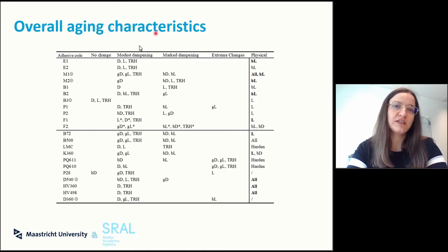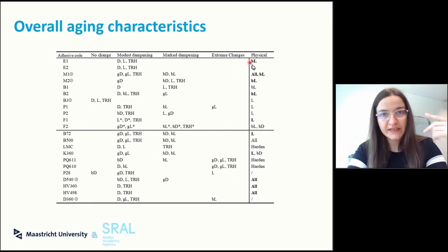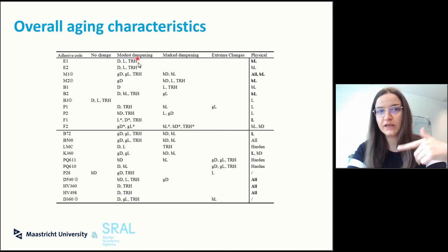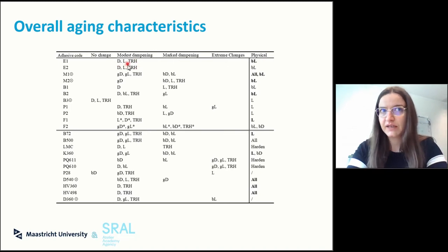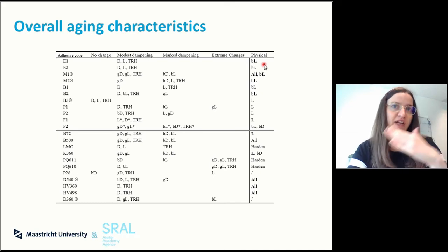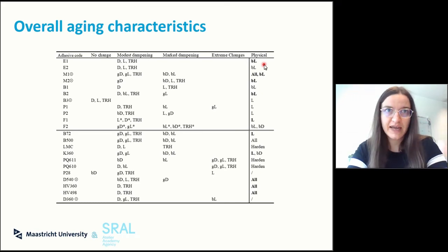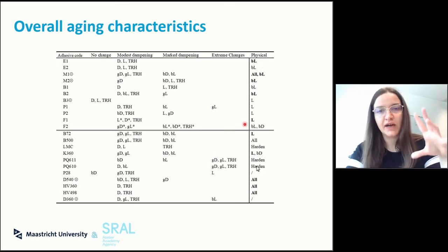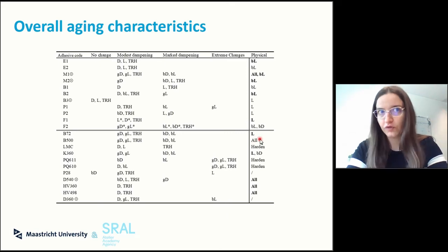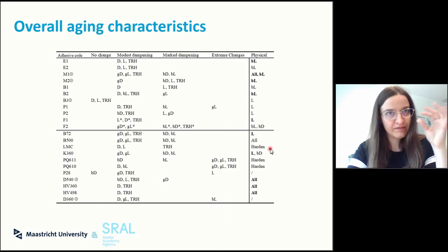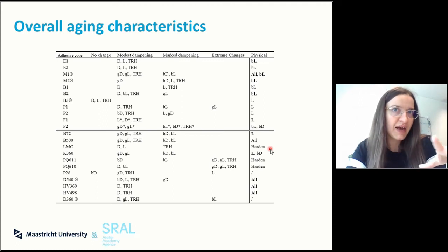So you can also see that regardless of maybe you see a modest dampening, when we indicate a physical change, here we can see that in this case there is a modest dampening of the light aged, but the light aged brush out has a very severe physical change that can be either brittleness, yellowing, scaling off. So this is all taken into account with this symbol label, and sometimes all of them have these changes, other times it is a very specific flag that we want to give, which is, for instance, the hardening.